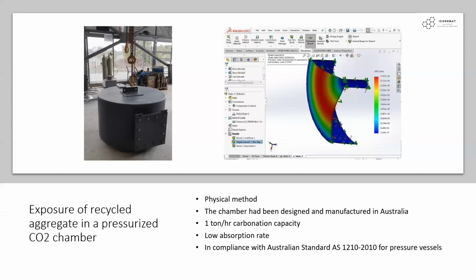The physical process is as simple as this. So you pour the recycled aggregate inside this container, inside this chamber, close the cap and seal it, and then introduce the pressurized CO2 via the allocated nozzles for a certain period of time. And your carbonized aggregate is ready after, say, 1 or 2 hours.